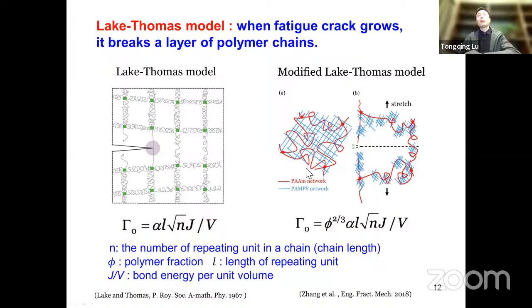So now we modify this Lake-Thomas model to account for the tough hydrogels. In the tough hydrogels, first we have two networks. When the fatigue crack grows, we assume that the short network, meaning the PAMPS network, has already broken. So this network does not contribute to the fatigue threshold of the double network hydrogels. The only modification is the water content. Phi is the polymer fraction, because hydrogel compared to rubber has water inside.